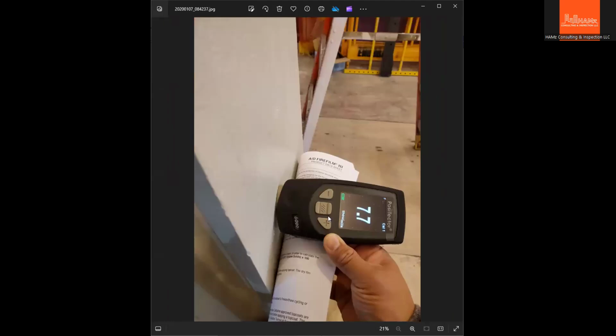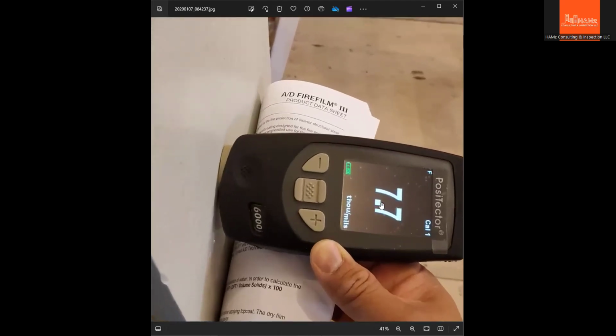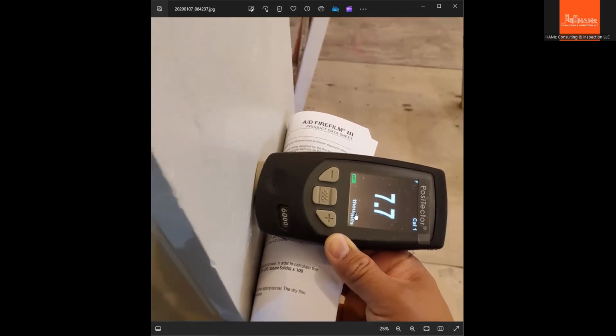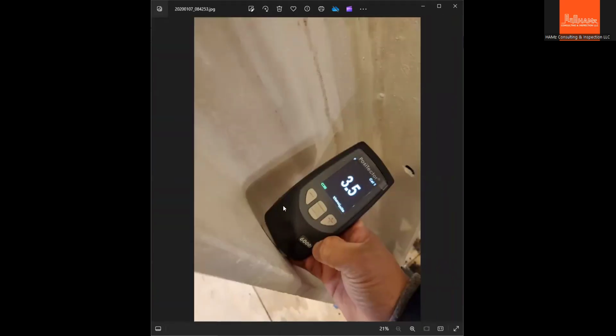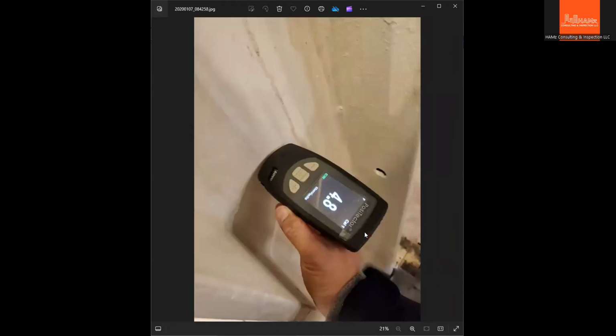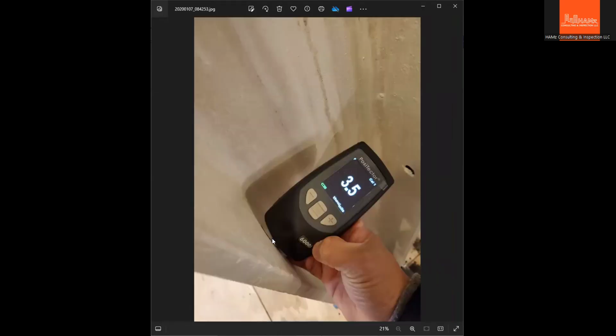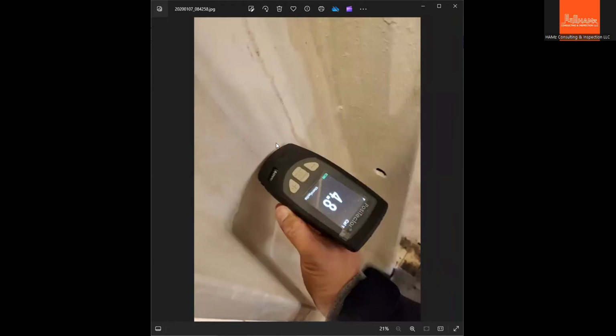And this is the equipment I use for thickness measurement. As you can see, this is 7.7 mils, thousandths of an inch, or mils. It's 7.7 mils. Currently, that's the thickness that has been measured. That's the inner side surface of the flange. This is the web.